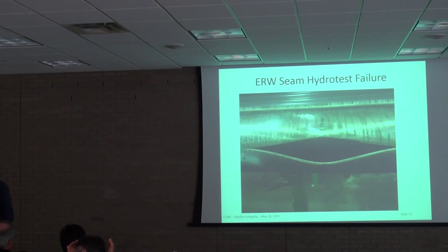I had experience on a 4-inch pipe similar to that, only it didn't open right up. We were testing it at 1800 psi, and the seam opened up enough to spray a mist out, and then once we dropped the pressure, it stopped. We cut that out and sent it down to, I think, Ohio somewhere for analyzing. Anything we made with that heat number on it, we cut it apart and scrapped it. Huge cost.